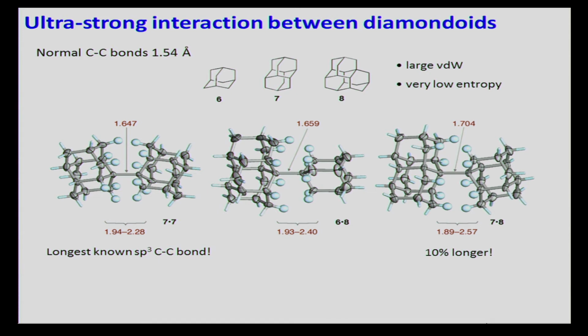The other reason why we think this is really a feasible idea is that people have found really unique behaviors in these diamondoid species or diamondoid materials. What I show you here is a few species of two diamondoids bonded together by a carbon-carbon bond. Now remember, in normal hydrocarbons, in normal organic molecules, the length of the carbon bond is about 1.5 angstrom, and the length of the carbon bond is a measure of how strong the bond is. Normal length being 1.5 to 1.6 angstrom, what we found was that in these species where two diamondoids are bound together by a carbon-carbon bond, the bond length is astonishingly long, about 1.7 angstrom, 10% longer than any other carbon bond that people have known of.